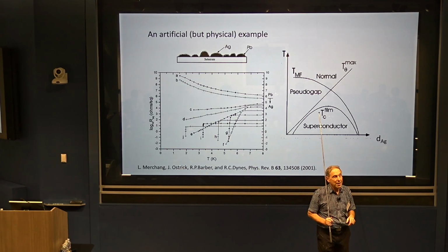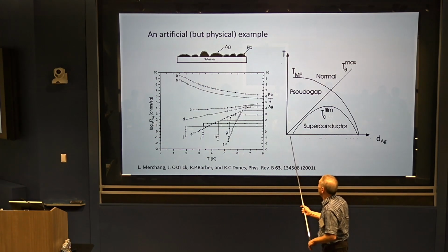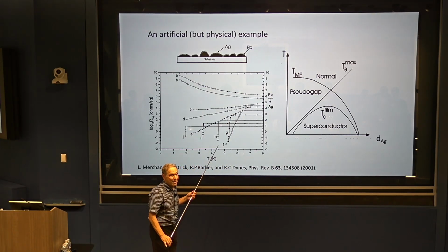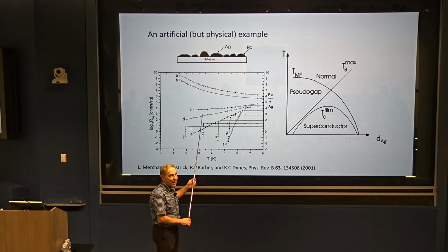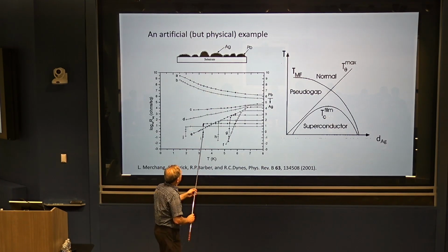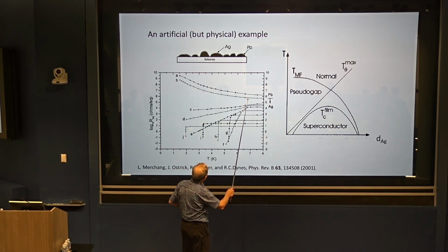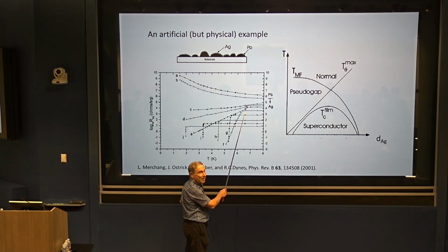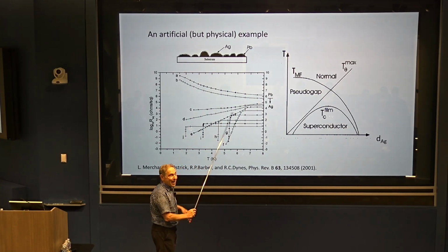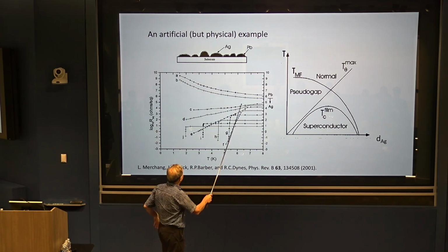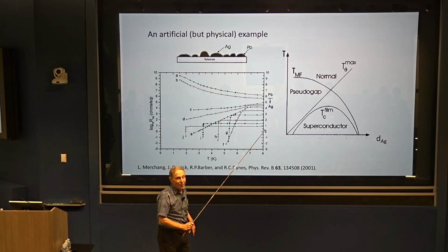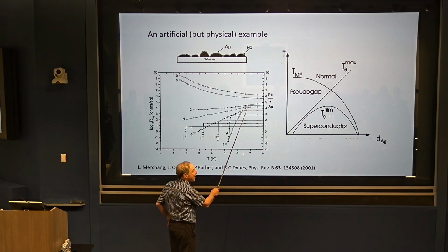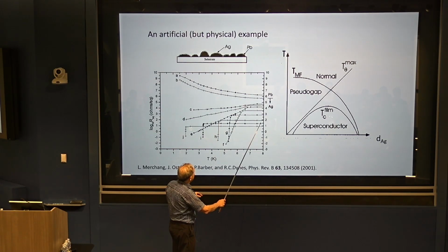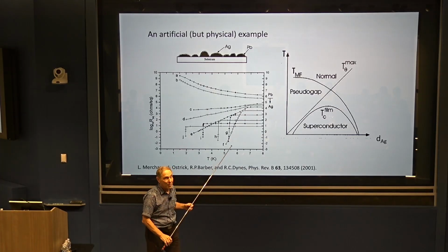So your TC, is that not the experimental TC, is that a transport TC? So everything here is from this curve. So this is the experimental data. Right, so it's transport. Yes. What I'm still struggling with, if you go back to your schematic. Let me just point out something here. As you first put on silver, I still see a deflection at the bulk TC of lead, and then I see phase fluctuations, quantum phase fluctuations. Who knows, but the resistance is dropped by 5 orders of magnitude, so it's superconductivity of some sort. But the scale of onset is set just by the superconductivity in the lead grain. But here, as I've got more silver on it, nothing happens down to a temperature that's way below, so you can see the suppression.